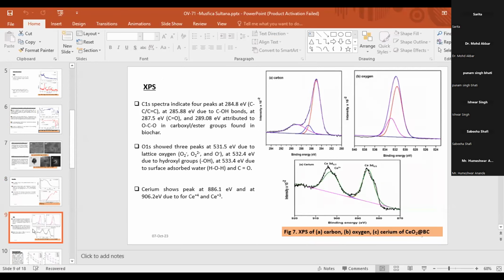From the XPS data, we have seen that the carbon 1s spectrum shows 4 peaks at 284, 285, 287, 289 because of several oxygen-containing bonds formed with oxygen. The O1s spectrum shows 3 peaks at 531, 532, and 533 because of lattice oxygen, hydroxyl groups, and surface adsorbed water. And cerium shows 2 peaks at 886 and 906 because of different oxidation states of cerium.